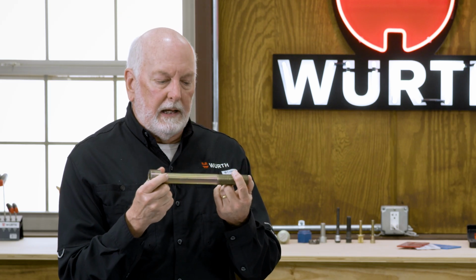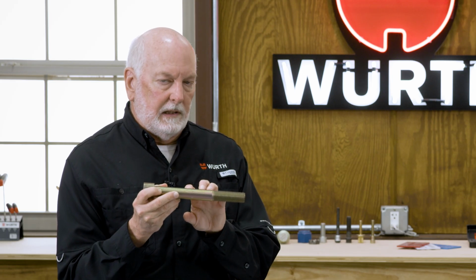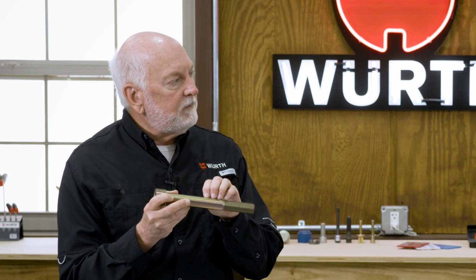So exactly. So Randy, let's talk a little bit about environmental hydrogen embrittlement. Okay, so environmental hydrogen embrittlement is also intergranular cracking, but it's not due to what we call internal hydrogen, where it's been put in there during the processes. This happens actually out in the environment. So if you think about this, we're talking about fasteners here today. This happens, by the way, in other steel components, but fastener finishes, most of the finishes are sacrificial. So in the environment, as that material is sacrificing itself, it's generating high concentrations of hydrogen, and you're right there on the surface. Right on the surface, right. So there certainly is opportunity for that hydrogen to make its way into the molecular structure of the steel.